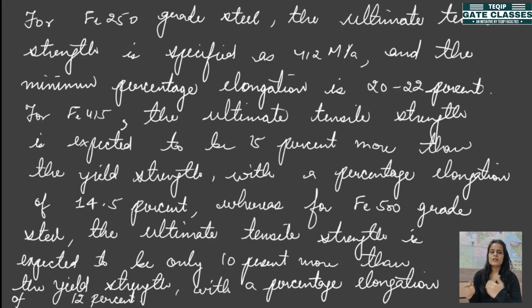Yield strength, ultimate strength and ductility values have been given. For Fe250 the ultimate tensile strength is specified as 412 megapascal and its yield strength is 250 megapascal and the minimum percentage elongation is 20 to 22%. Okay, for Fe415 the ultimate tensile strength is expected to be 15% more than the yield strength with a percentage elongation of 14.5%. Whereas for Fe500 grade steel, the ultimate tensile strength is expected to be only 10% more than the yield strength with a percentage elongation of 12%. Okay.